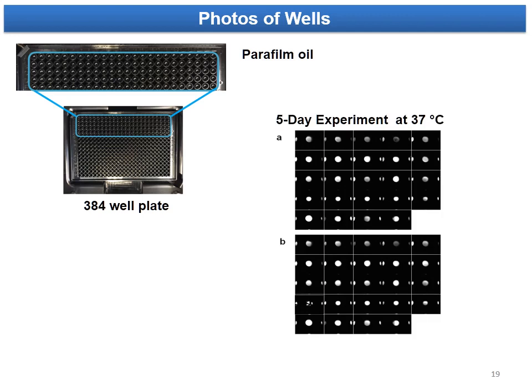The third stage involved acquisition of images and size measurements from each well of the plate. The fourth stage consists of analyzing the data collected over defined periods of time, using both cumulant and regularization methods. The panel on the right side of the figure shows tentative nanoparticle configurations tested in BSA medium. After plating the nanoparticles in the 384-well plates, I added parafilm oil on top to prevent loss of sample — a very important step if you plan to acquire data over a longer duration of time.